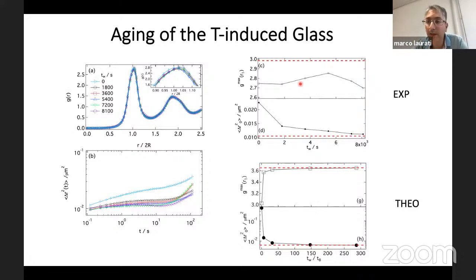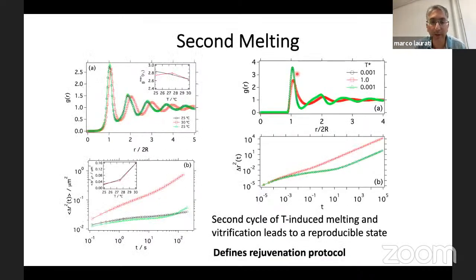And it might be that when you suddenly increase the size, so the volume fraction of the system, through the temperature change, the structure of the liquid remains to some extent frozen in. And as you see, since the dynamics are slowing down more and more, of course, this is not favoring the evolution of the system. But okay, understanding this effect indeed still needs some additional experiments.